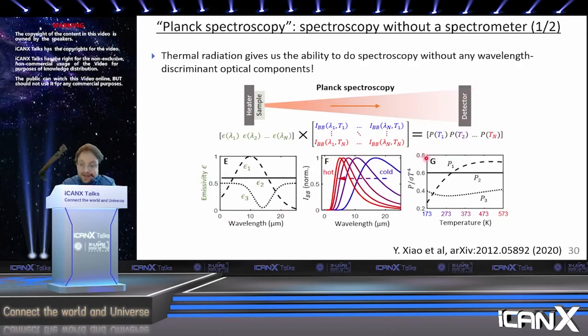What you get then is the power versus the temperature of the sample, so the measured power on the detector versus the temperature of the sample. In this case, I'm also normalizing the power by T to the fourth so that all of these fall on top of each other. One thing you can see is that different emissivity spectra map to different shapes of the thermally emitted power, essentially because the spectrum multiplies the Planck distribution, and the Planck distribution changes with temperature. So you have this non-trivial dependence of the thermally emitted power measured on the detector versus the sample temperature. You can imagine inverting this, going from the measured power versus temperature to figuring out what the emissivity is using computational techniques. That's what Planck spectroscopy is and how it works.